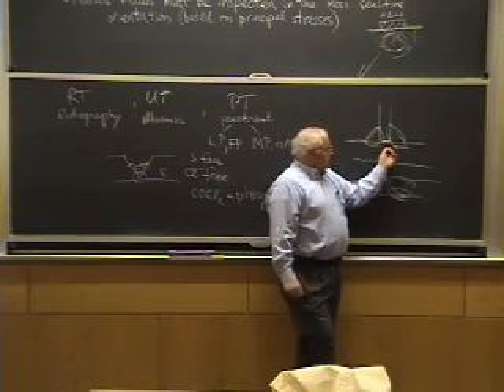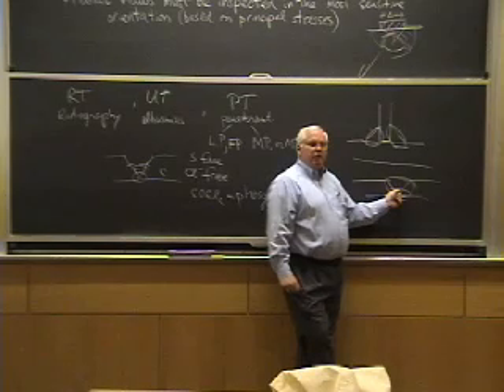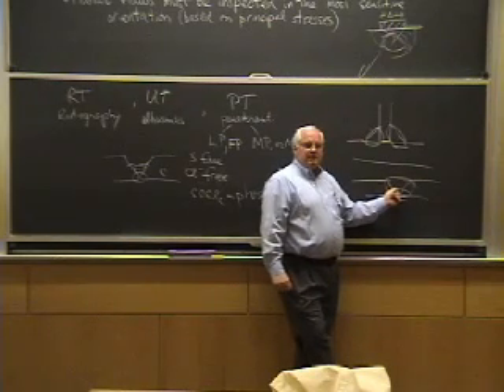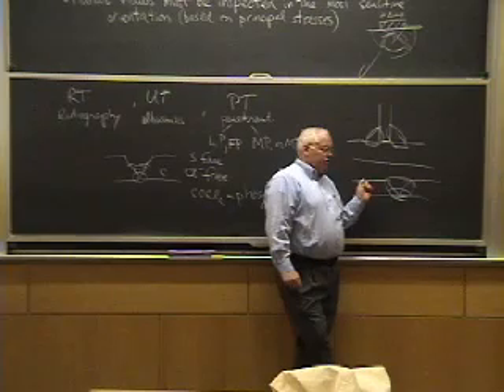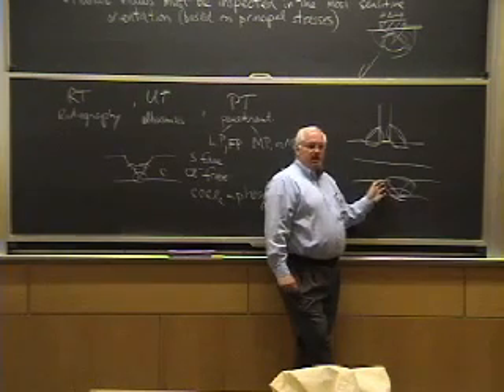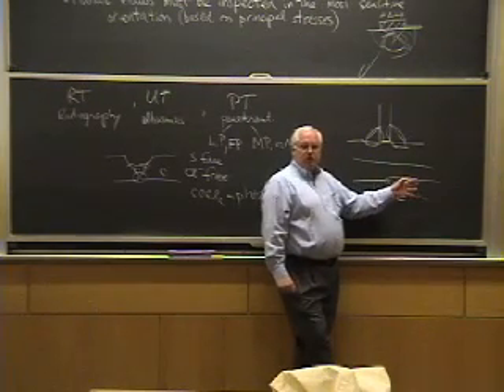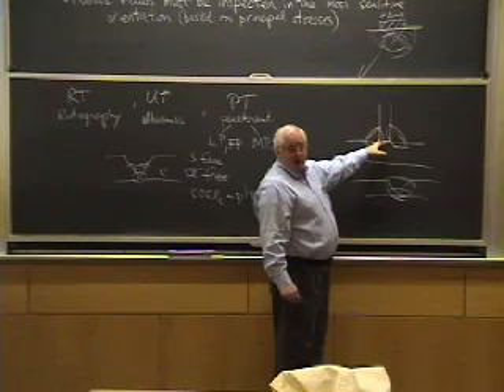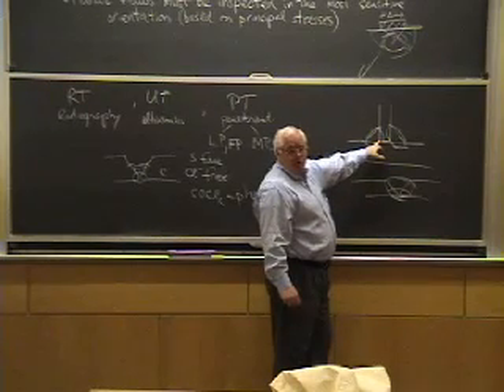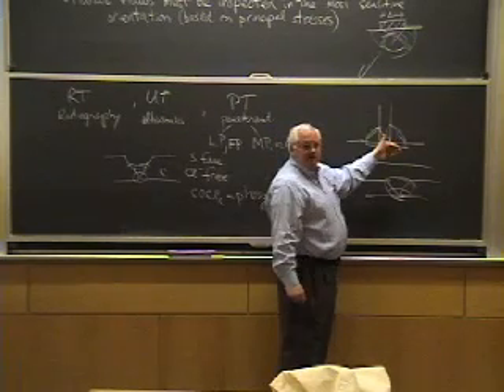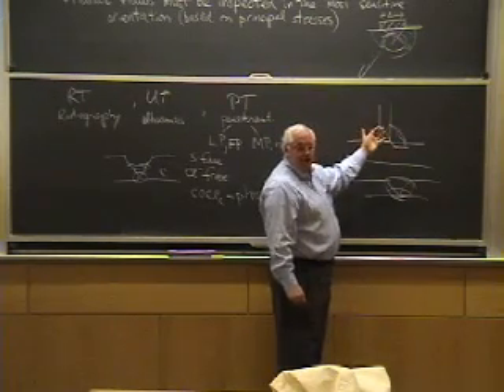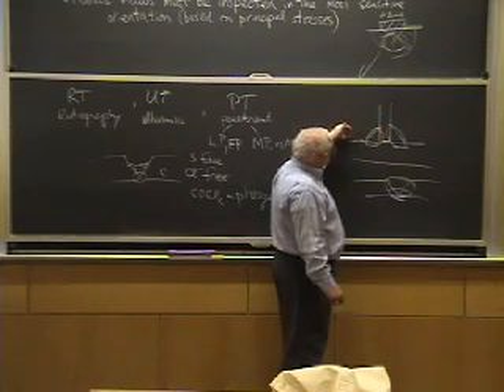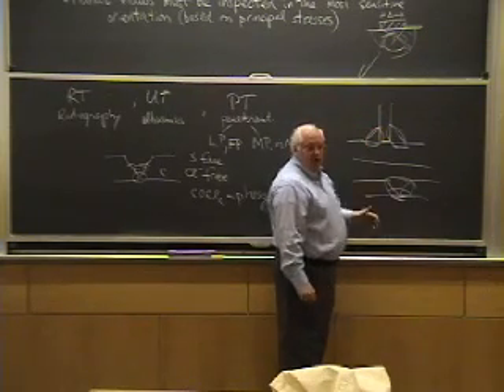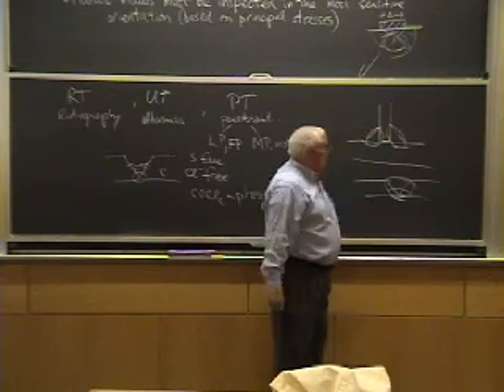So fillet welds are the most common. Groove welds are easily tested by ultrasonics or X-rays. You get a projection through here, you can bounce a beam through here, you basically have homogeneous, uniform material. This is a pain in the neck to do ultrasonically or with X-ray. You've got different thicknesses for X-ray, so you can't get a very uniform exposure. With ultrasonics, well, gee, where are you going to bounce the wave in here? It's too complex a geometry.